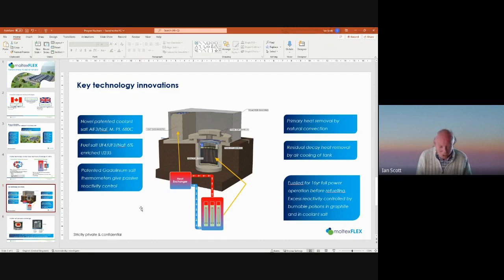This is also not an entirely original idea. These have been suggested for fast reactors using molten lithium as the liquid. That's never been actually put into practice, to the best of my knowledge. The advantage of the gadolinium salt is twofold. One is it is much more chemically stable than molten lithium. The second is it doesn't produce tritium in large quantities, which lithium inevitably does. And therefore, you have a much smaller radioactivity problem to deal with.